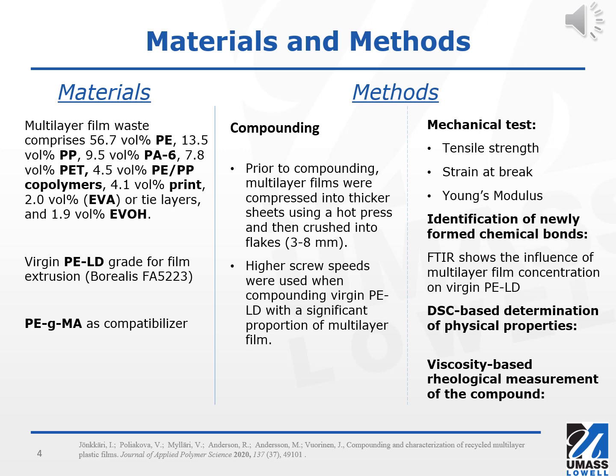In this slide, we will talk about the materials and methods used in this study. In terms of material composition, multilayer film waste is composed of 56.7% polyethylene, 13.5% polypropylene, 9.5% polyamide, 7.8% PET, 4.5% PE/PP copolymer, and 4.1% print with 2.0% EVA along with EVOH. So compounding was basically done with virgin LDPE grade material intended for film extrusion.